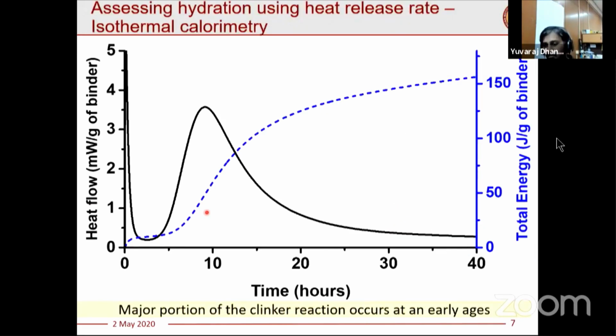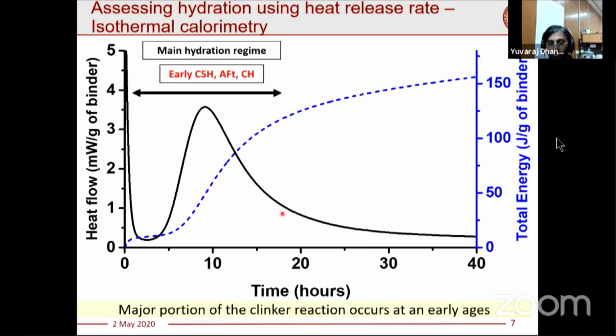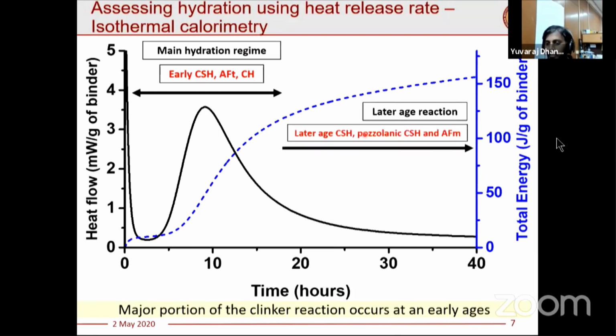So generally, SCM hydration is assessed by a calorimetry experiment, where because cement hydration is an exothermic reaction, you can measure the heat release rate, which gives a fair estimate of the reaction rates. So you have the main hydration peak. This is the cumulative heat, which is the energy of the material. So you see a rapid increase in energy within the first 1 day, and then the reaction slows down. So you have the main hydration region, where you have formation of early CSH, ettringite, and CH, and then the later hydration period, where you have later age CSH, pozzolanic CSH, and other hydrate phases.